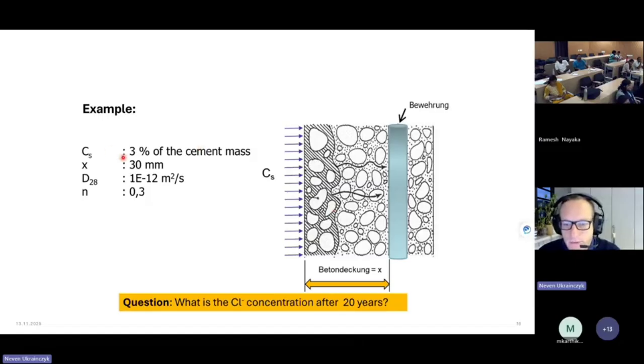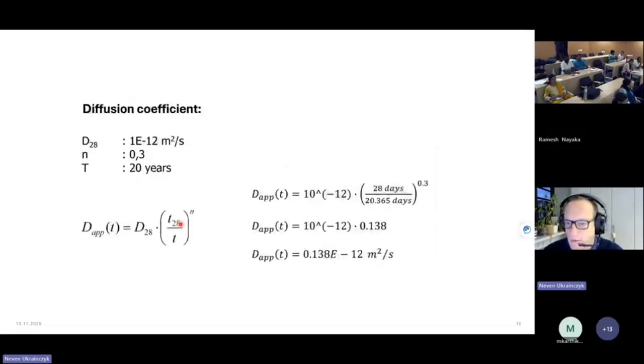So here's an example. We will solve this example later. Let's say that the surface concentration, that's the boundary condition, is 3%. This can also change with time actually, and there are models where you can change this with time, but in this simple model, let's fix it at 3% of the cement mass. We have this diffusion coefficient and the cover depth is 3 centimeters. And we have the n coefficient of 0.3, so we can plug in these values and then you can see how this apparent coefficient is actually reducing.